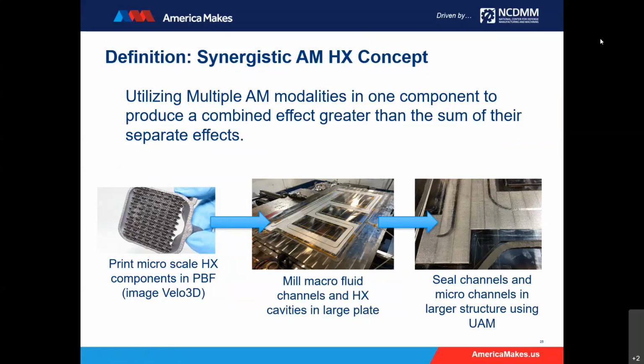But what if we had some thermal structure that we're working on? Let's say it's 6 foot long. It's a very large thermal structure. But in most cases, when we have these thermal structures, there's discrete regions where heat is being pulled out, right where we have an electronics chip, right where we have a process. So what I would propose is maybe we could print very fine featured thermal cavities, if you will, out of, say, powder bed fusion. And we print those so that we have a very, very high rate of heat rejection from our part. But we need to integrate that into a much larger part.